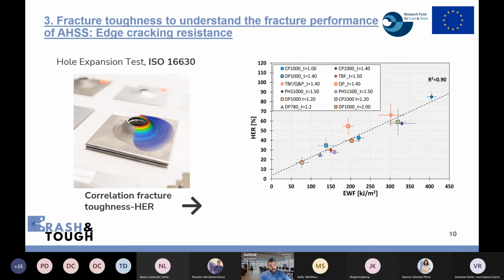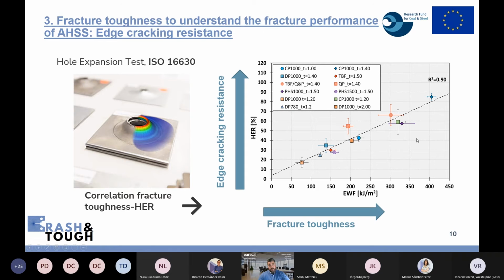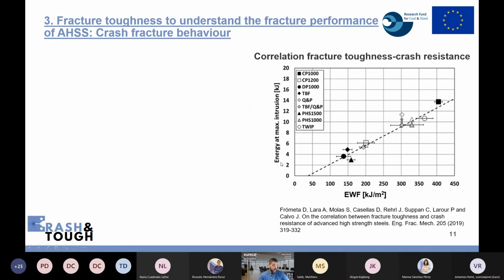That's what we have done with the essential work of fracture, and here you can see the correlation between the hole expansion ratio and the essential work of fracture for a wide range of advanced high-strength steels, including first and third generation steel grades of different strength classes, from 800 to 1500, where we can see the linear correlation, the good relationship between the fracture toughness measured through the essential work of fracture and the hole expansion ratio. So tougher materials, with higher crack propagation resistance, also show higher edge cracking resistance.